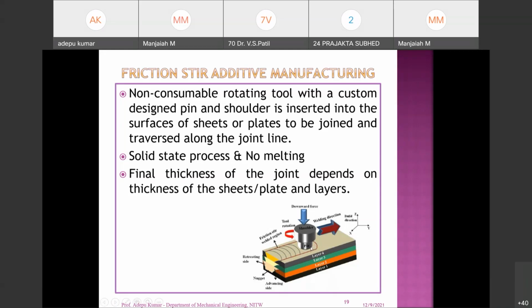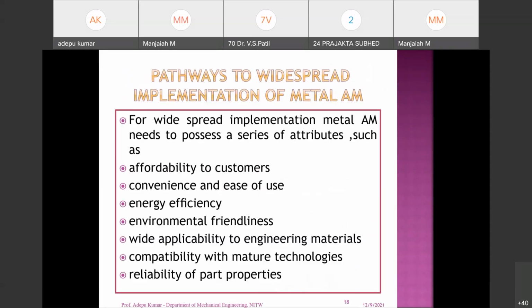If you are not providing sufficient heat generation, it means indirectly you are not giving sufficient rotational speed and welding speed. That leads to creation of a slot. That is improper material flow. Why improper material flow? You are not giving sufficient heat to that material, so it may not reach the recrystallization temperature. When it does not reach it, movement of the material cannot happen. So that is a very important aspect in the friction stir additive manufacturing process.